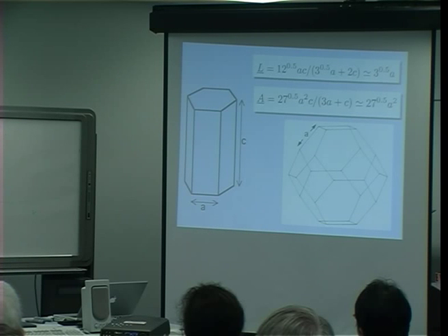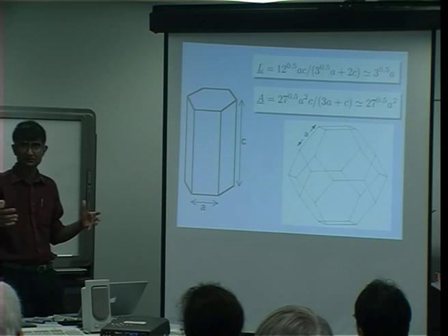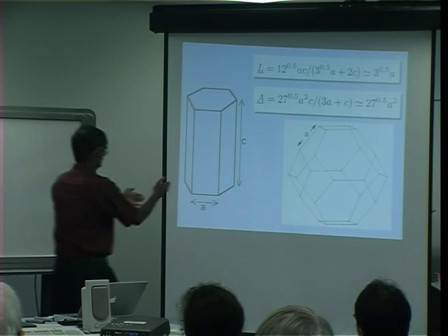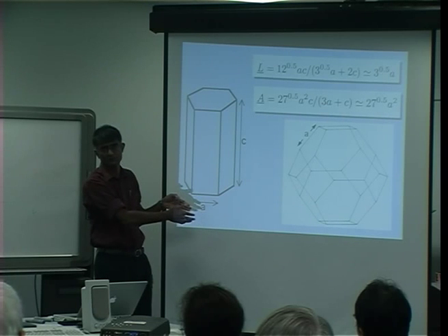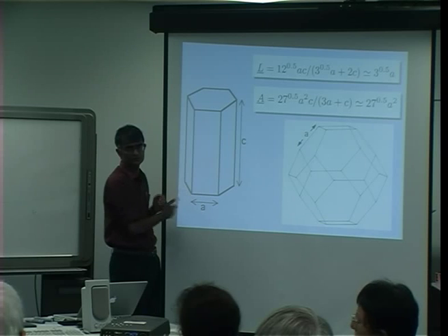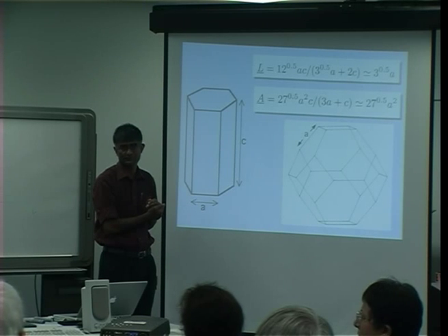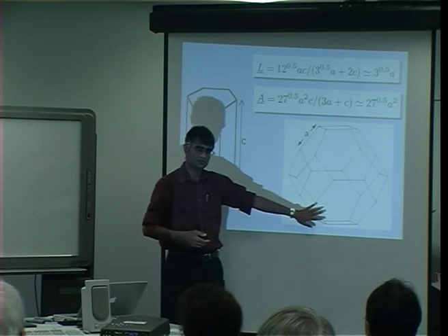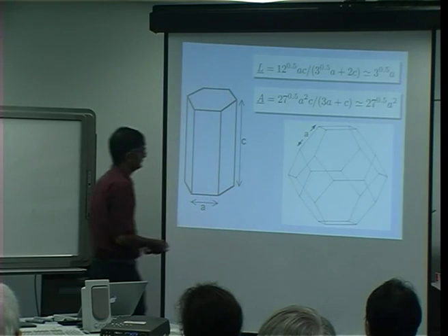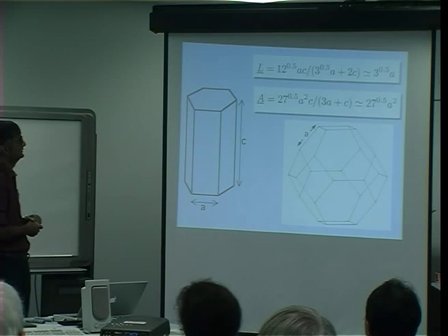Now, if you look at the shape of the columnar austenite grains that you have, they are in three dimensions like hexagonal prisms. Okay, so they are very long along the C-axis, approximately 5 millimeters typically, and something like 100 micrometers wide. This is what the shape of a normal grain looks like in an ordinary steel. It's isotropic, almost. Okay? So we call it an equiaxed grain structure.